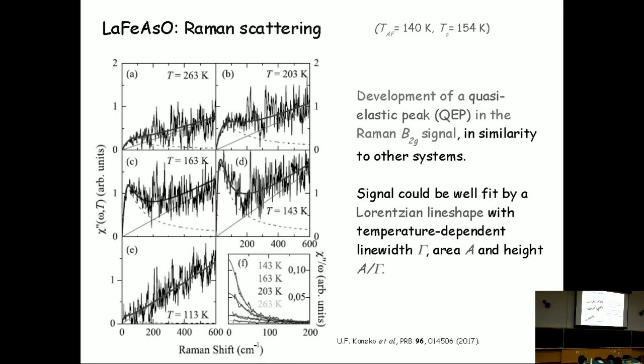which turns out to be omega times a Lorentzian curve, and then this purple component is related to some 2-magnon Raman scattering that peaks at very high frequencies, which cannot be seen in this scale, but doesn't interest us very much. What interested us is this dotted blue curve here, which starts developing as we cool down. At 163 K, just above the orthorhombic transition temperature, you already have a very well pronounced signal. At 143 K again you have a very pronounced signal.